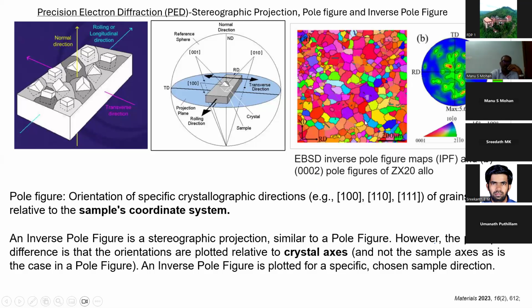You can see here, this is basically the 002 pole. The 002 pole is actually hexagonal - a 4-axis system means it is in the hexagonal crystal system. So it is actually the 002 plane in the hexagonal system, basically along the C plane, which is what you are asking it to plot. So you see here towards the center, you see an orange color, whereas far from it you see green color, meaning when it's orange, it is perpendicular to the plane of the board - that is, it is normal to RD. So these 002 plane normals are perpendicular to the plane of the board, whichever screen we are seeing.